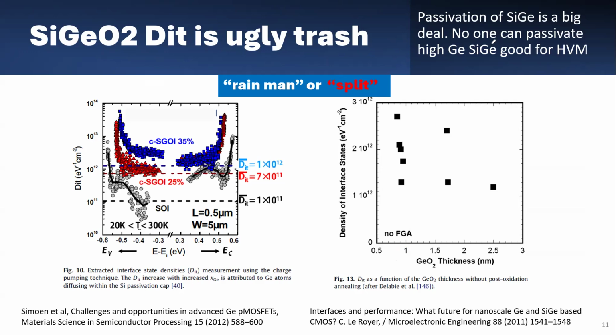So overall, passivation of SiGe is a big deal. By the way, no one can passivate high germanium SiGe well enough for high volume manufacturing. No one. People publish papers left and right about how low they could passivate SiGe, but at the end of the day, it can never really be put into HVM for high germanium SiGe. TSMC said they did it for 5 nanometer PFET. So I think that germanium is borderline 30%. There's no way to go any higher. And I still have some doubts on that. Let's talk about that later, okay?